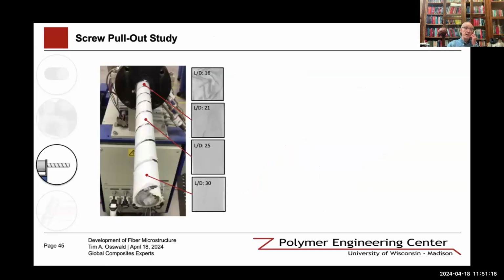The next thing that we did was to do pull-out studies in extruders to be able to understand what occurs in the plasticating unit and to see how dispersion advances throughout the system. You can see here at L over D, going from L over D 16 to 30. At L over D 16, you still have a relatively undispersed system, and then at L over D of 30, you are almost completely dispersed, which is what you want.